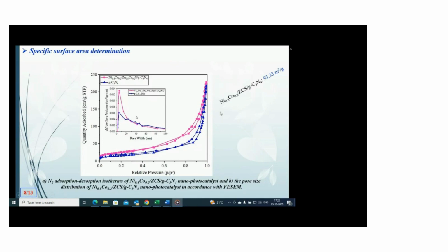In comparison to pure g-C3N4, the nanophotocatalyst exhibited an increase in specific surface area. This increased specific surface area provided a higher density of active sites for redox reactions and is advantageous for photocatalytic application.